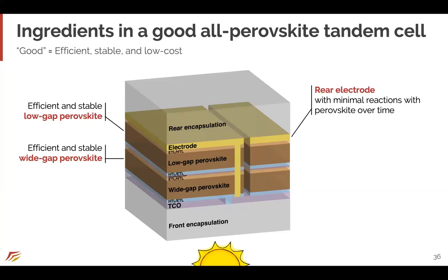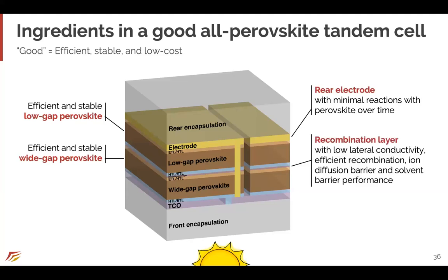Maybe the most important layer in a tandem is the recombination layer, which goes between the low and wide gap perovskites. You have to electrically connect the subcells with this layer by efficiently recombining holes from one cell and electrons from the other. And a couple of design considerations: you do need to make sure that this recombination layer isn't too conductive laterally, so you avoid coupling the shunts. You also need to block ion diffusion between the subcells, and avoid damage to the bottom cell during processing of the top cell.